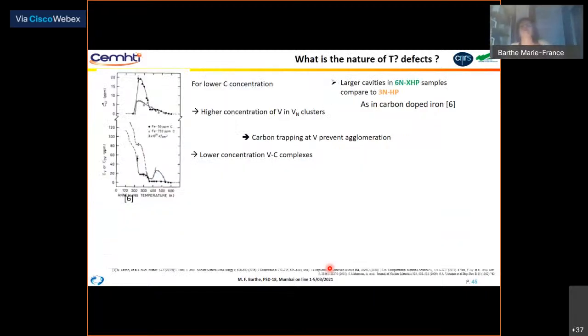So what is the nature of this T trap? And we come back to the past, to this study from Rhiannon and co-workers in carbon-doped iron, where they demonstrated that the formation of vacancy-carbon complexes prevents the agglomeration of vacancy clusters.